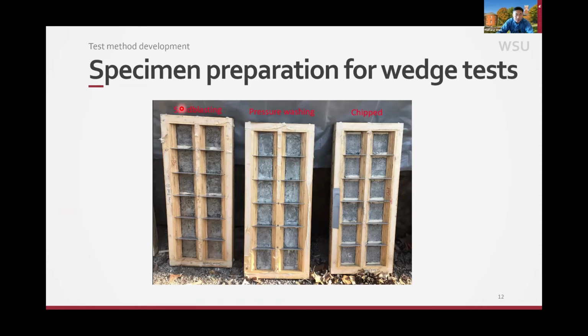So we use three different methods, or specifically four. One is you use sandblasting to prepare the concrete surface, to make it a little bit rough, or use the water pressure method to make the surface a little bit rougher before you apply the shotcrete, or you use this chipping method, to make the surface even a little bit rougher.